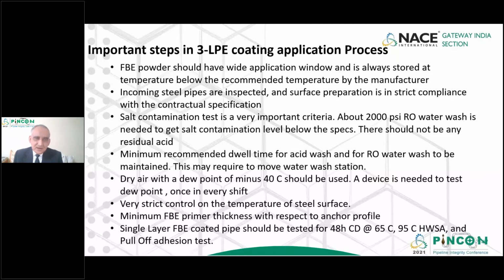Second, the inspection of incoming pipe is also important, so that the incoming pipe does not have any defect before the application process. A salt contamination test has to be done on a blast cleaned pipe, and it should be ensured that it is within the limit. Otherwise, there is a recommendation to use a very high pressure water wash. Also, it should be cleaned using phosphoric acid so that all the salt gets combined with the acid, which is followed by water wash. So the acid should also be removed.